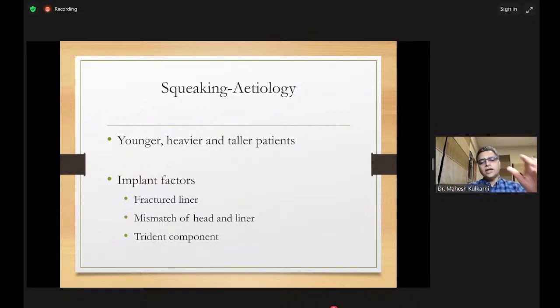liner, and we had failure with the earlier generation ceramic with the Trident component. The problem was that the Trident ceramic insert had a metal elevation, and that probably led to impingement of the neck on the elevated metal liner of that ceramic, and that caused squeaking.